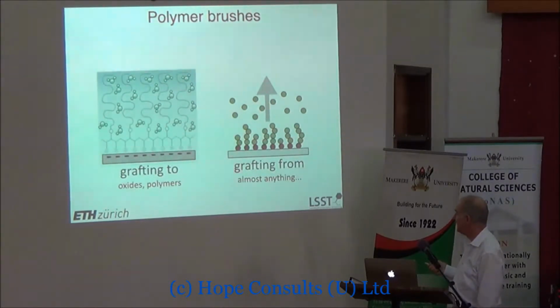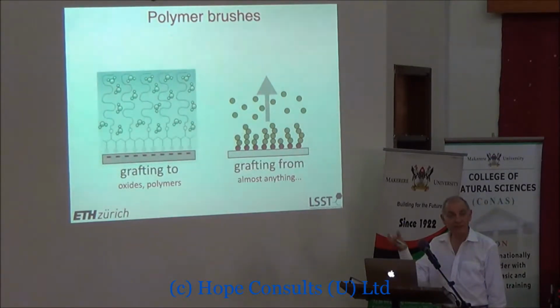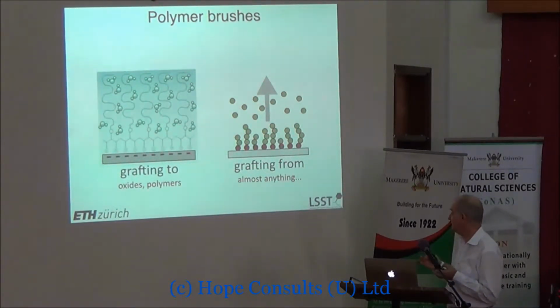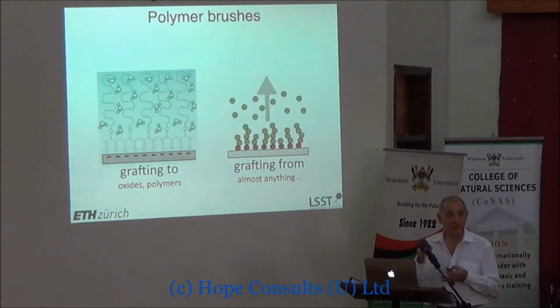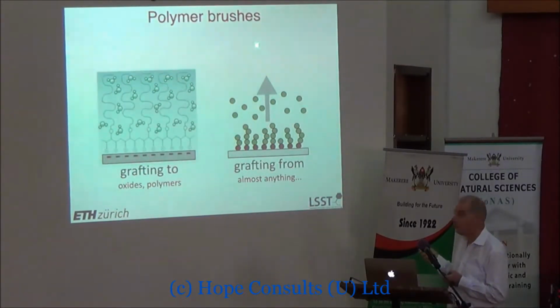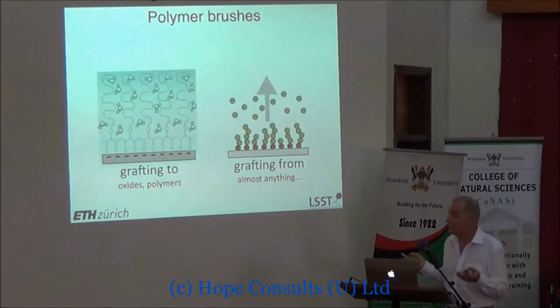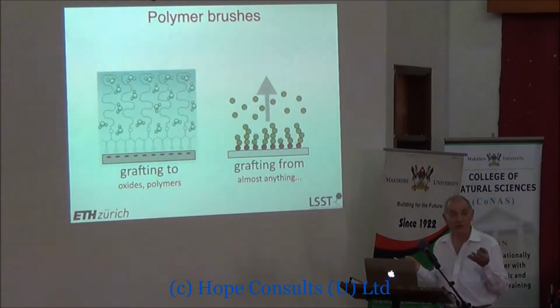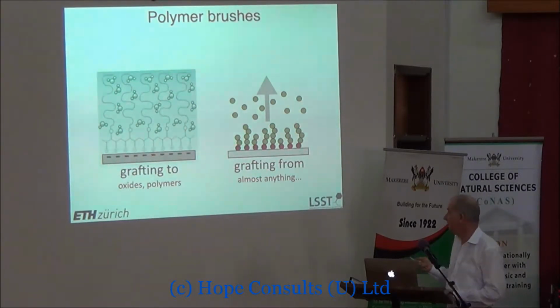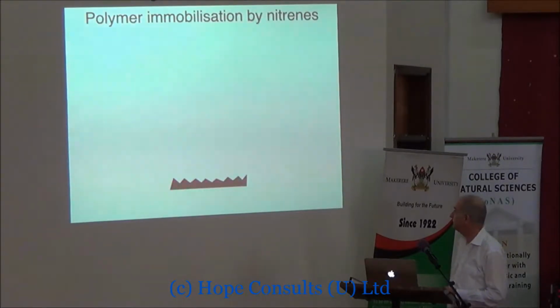What's a bit more tricky is to put a layer of initiators onto a surface, and then to do polymer synthesis on the surface. So we actually grow the polymer out of the surface. Obviously that requires more chemistry, more in situ synthetic chemistry. The advantage of doing that is you have complete control over the composition of the brush. You can change the monomer as you grow the polymer, for example, to have different functions as you're growing. And you can grow it as long as you like, so you can make really very long polymer chains on the surface. So grafting to and grafting from are the two approaches.